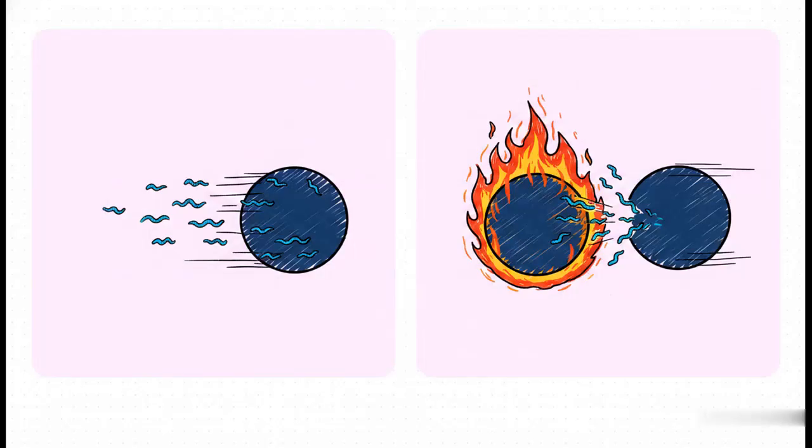But here is the crazy twist. Higher temperatures actually speed up the kinetic rate of diffusion, so the dispersant rushes through the liquid super fast to coat those freshly broken particles. Awesome, right? But thermodynamically, because adsorption naturally releases heat, forcing excess heat into the system pushes the equilibrium right back in the opposite direction. If it gets too hot, the Gibbs free energy balance shifts, and you literally start boiling the protective dispersants right off the pigment. They fall right off, leading to massive desorption and instant reaggregation.